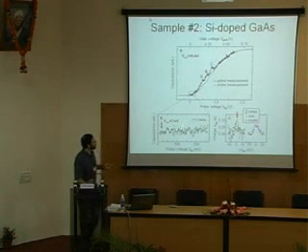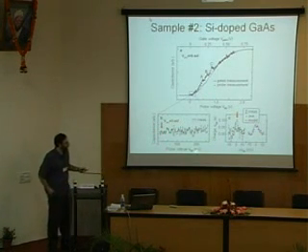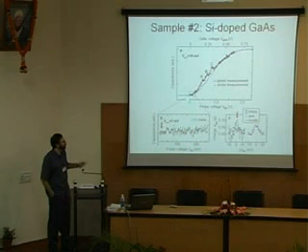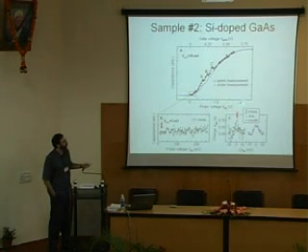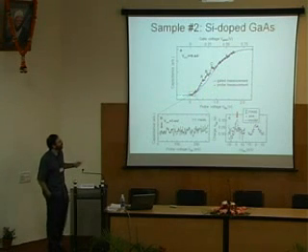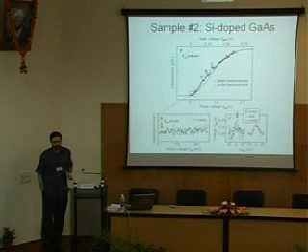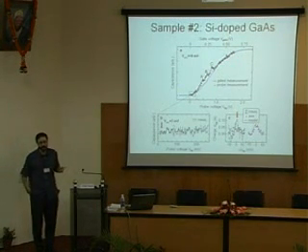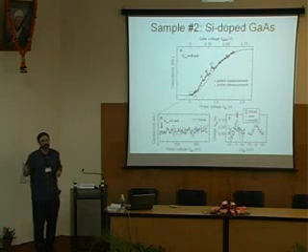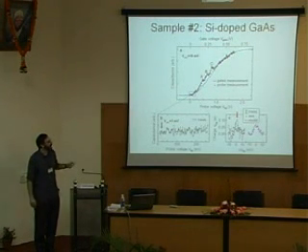All right, so this was a fairly small voltage range, 0 to 250 millivolts. What if we go over a bigger voltage range? The same sample, we're going to go all the way up to 1.5 volts or so. This data was just a small subset of the total thing that we're ramping over now. We see an overall slope structure. This occurs for essentially the exact same reason as in the silicon sample. We can get an accumulation layer forming near the surface. That's a much bigger capacitance, and this gives us this background.